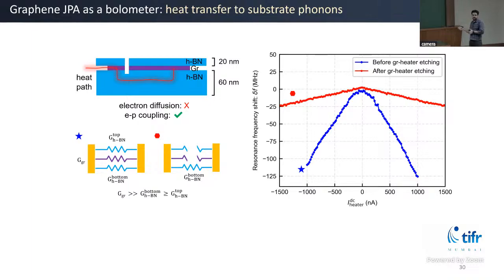and also to substrate phonons. As you know, at low temperature, at 10 millikelvin, you would not expect many substrate phonons because they are frozen at low temperature. So they won't activate as a heat transfer path. For that, what we tried is to do an etch in the graphene. By doing that, we are now cutting this heat conduction path to graphene. So the only thing you are left with is the substrate phonon.